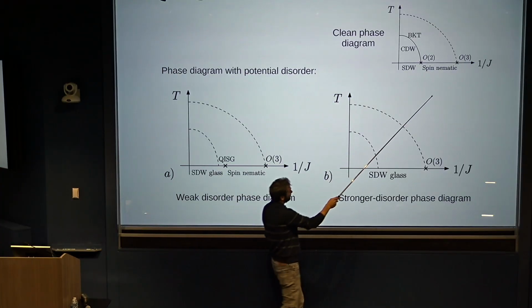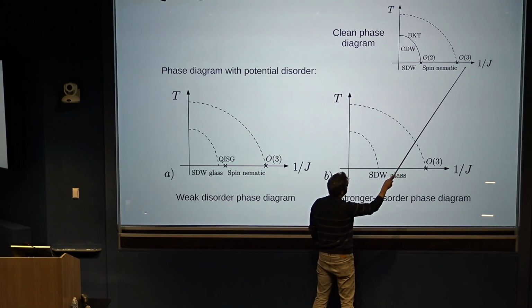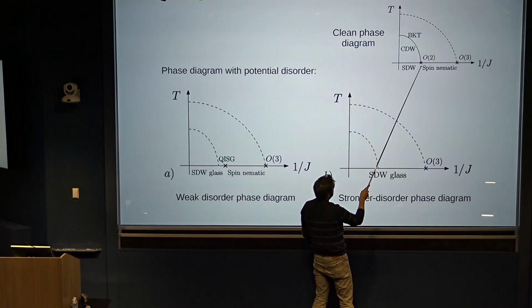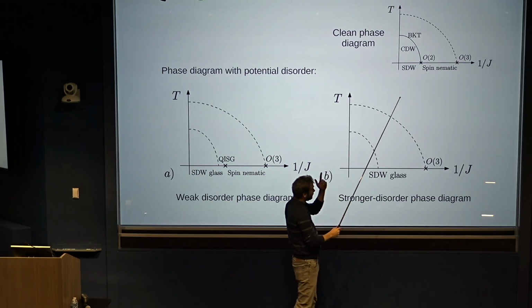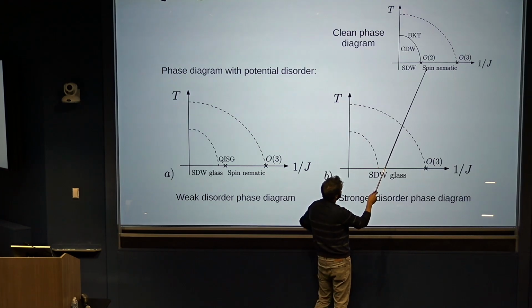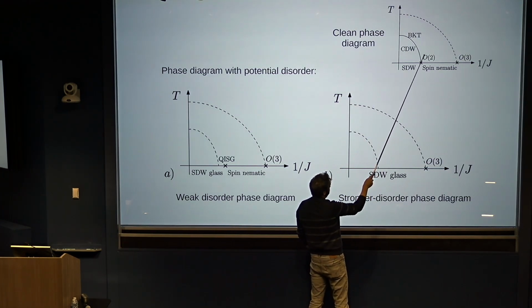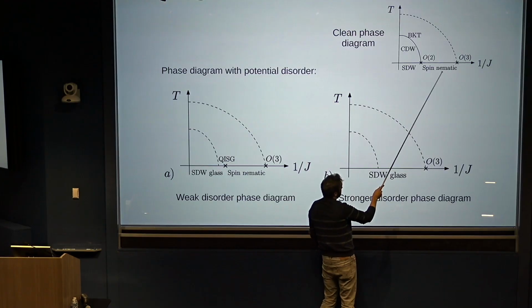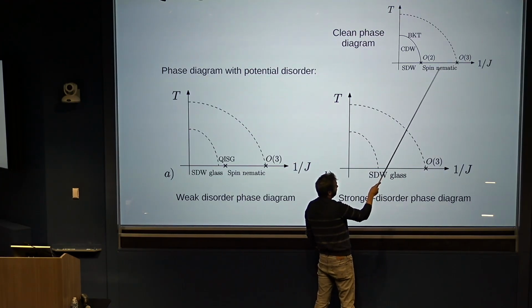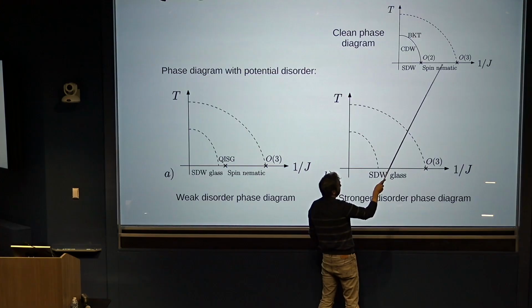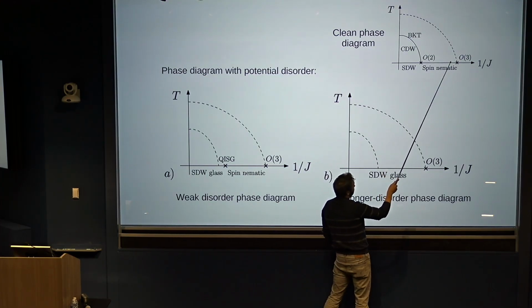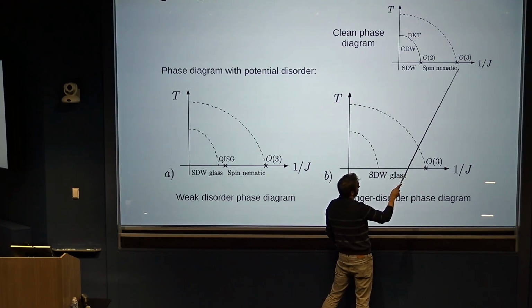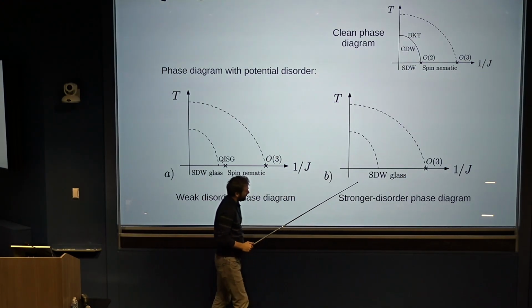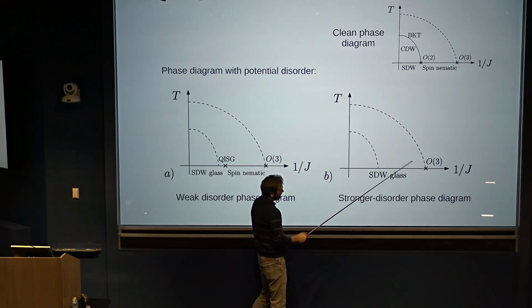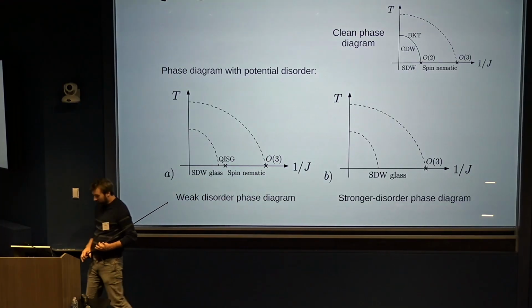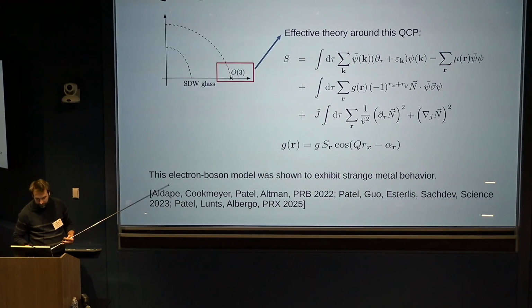This transition is basically standard Wilson-Fisher, because the Fermi surface reconstruction here happens if you couple it to fermions. So, if you couple this order parameter to fermions, there will be Fermi surface reconstruction at the O2 transition. But the spin nematic order parameter has no Yukawa coupling to the fermions. So even in the presence of a Fermi surface, this O3 transition is basically still Wilson-Fisher. But now with disorder, that's no longer true. And this O3 transition belongs now to a different universality class.